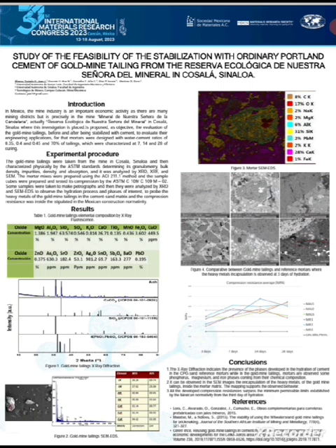Some fragments of the test were taken to make petrographs, and then they were analyzed by XRD and SEM EDS to observe the hydration process and phases of interest, to prove the heavy metals of the gold mine tailings were in the cement sand matrix and the compression resistance was inside what is stipulated in the Mexican construction normativity.